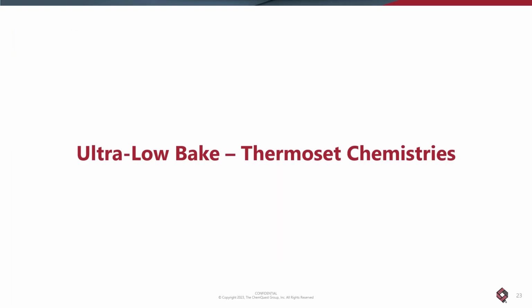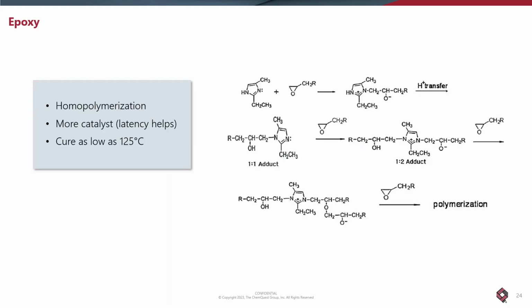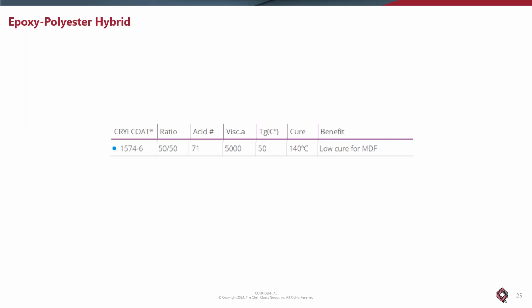Let's talk about the ultra low bake stuff, the stuff that's gonna give you the ability to cure below 150 and maybe kind of sneak up upon that 120 degrees Celsius with some caveats attached to that chemistry. With epoxies, it's a matter of driving the cure down, and with epoxy chemistry, and this is Bisphenol A type epoxies in particular, you've got a homopolymerization route you can do, and again, surprisingly, you can do this with imidazole catalyst, and it works. It's a pretty hot system. You got to be careful, but we can drive the cure temperature down into kind of that lower range of about 125 Celsius.